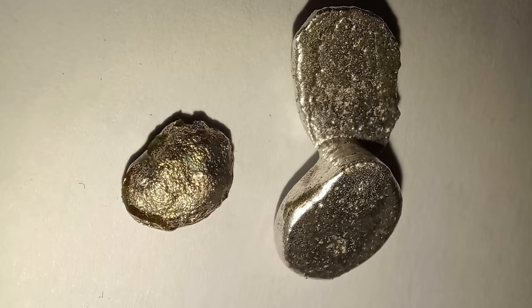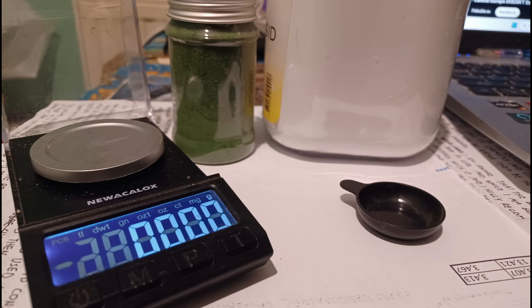The system I have works for silver. With palladium, I ran into a problem that forced me to melt it directly in the arc. I believe that, with a high temperature flux, melting palladium in a crucible will have lower losses. I will do some more research and experiments, and I will post an update when I get a working system that can be used for melting platinum group metals.